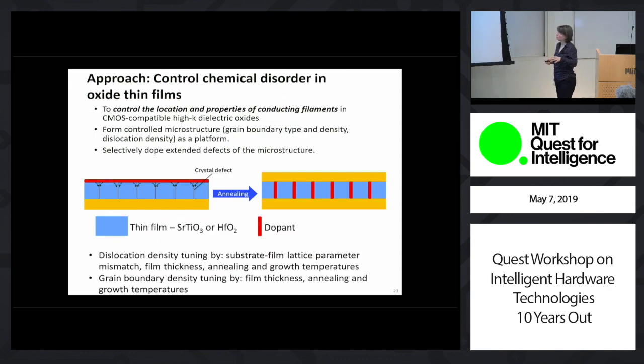So then the goal of our work is to control the location and properties of those vacancy-induced conducting filaments in CMOS-compatible high-K dielectric insulating oxides, such as hafnia and strontium titanate. We started from hafnium oxide. And the starting point is to first control the microstructure of these films. That is, we want to not deal with random grains or randomly distributed grain boundaries, but a well-aligned grain texture which can give us similar grain boundaries and rather well-defined paths.